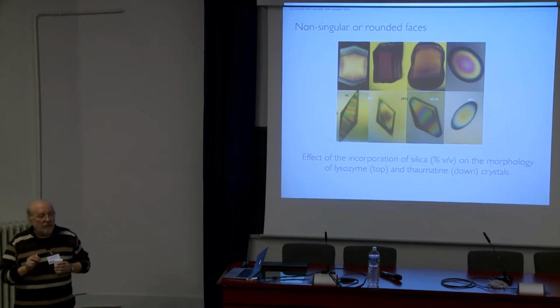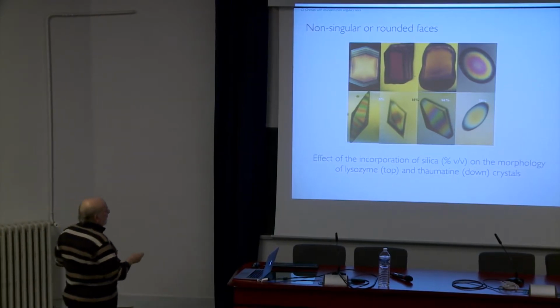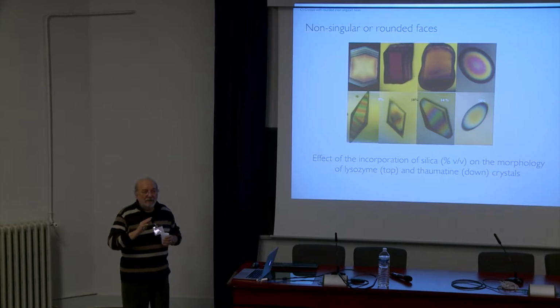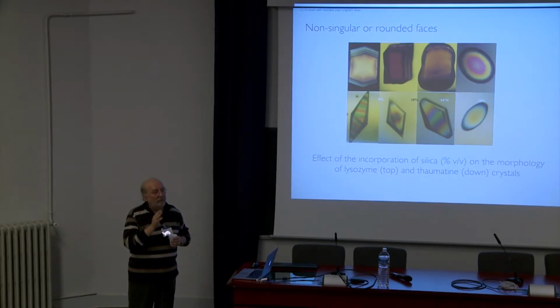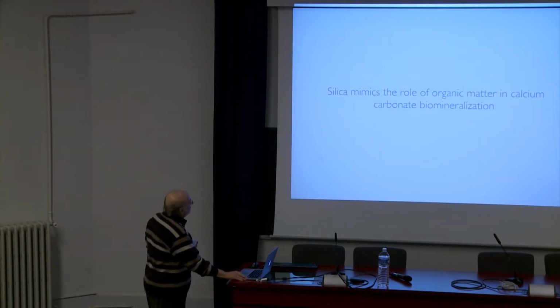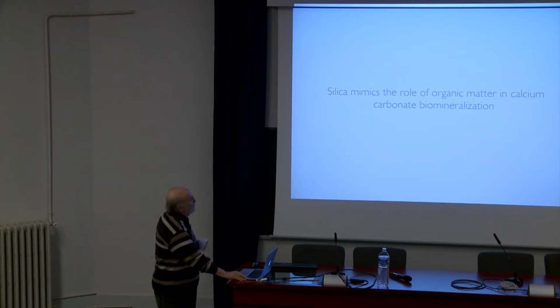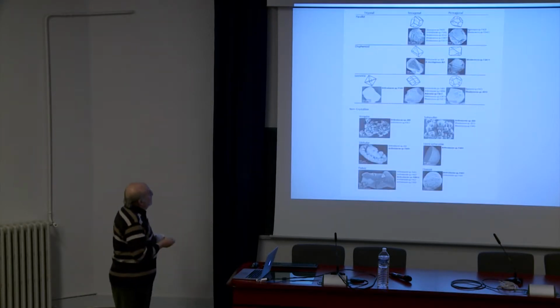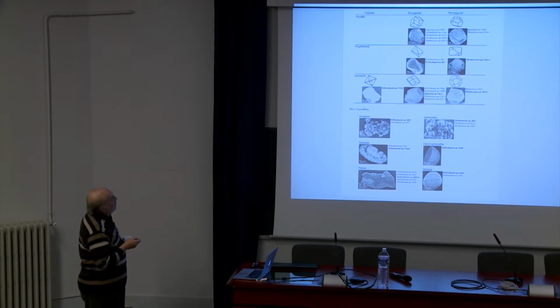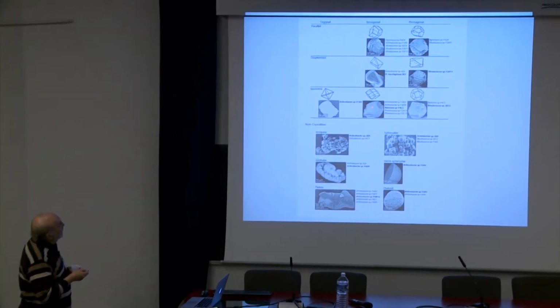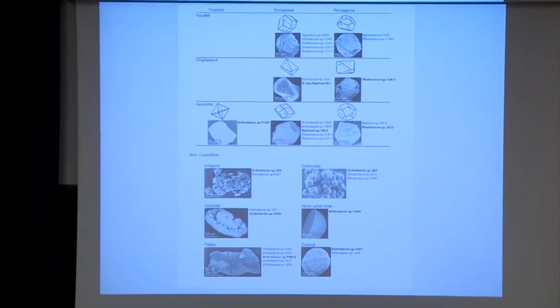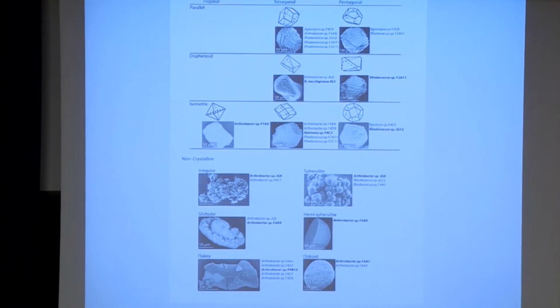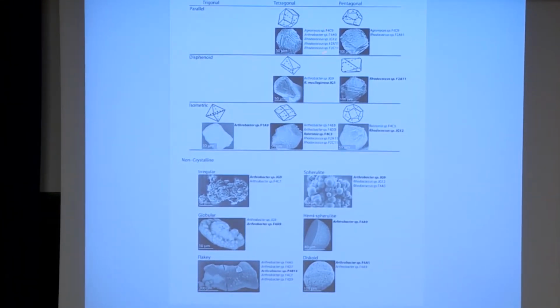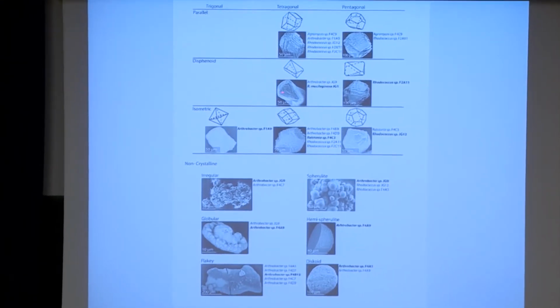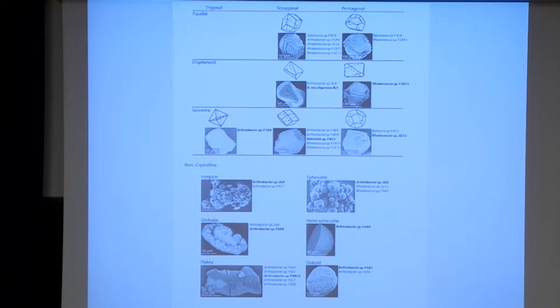Okay, so as soon as you have impurities, polymeric impurities in the growth system, you can really remove the characteristic property of the crystal to have flat faces, to have rounded faces. Okay, so that silica mimics very well what organic matter does with calcium carbonate crystallization. So these are crystals of calcite, grown from biominerals. You cannot see clearly the flat faces because the organic matter induces the modification of the flat faces to form non-singular faces, curved faces.